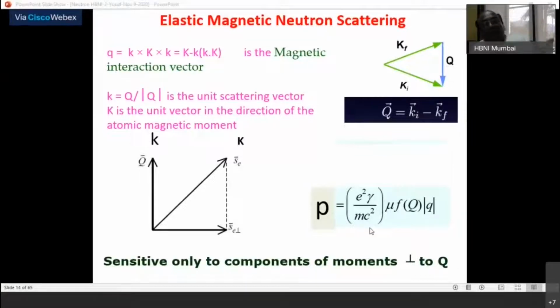Though in a relative sense it is 4 orders of magnitude weaker than the electric field scattering, since the incident flux is very, very high, that so-called weaker component is still a measurable quantity, because you have filtered out the charge part by a suitable analyzer. So the good statement would be that if you go to powerful synchrotron facilities, there you can even do magnetic X-ray scattering, like magnetic neutron scattering.